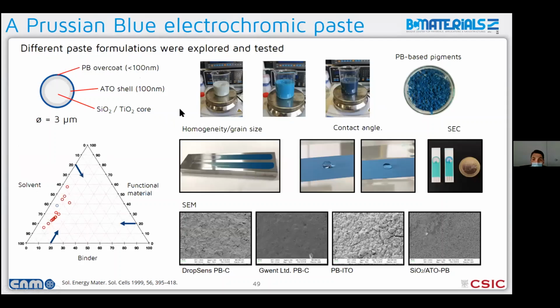So to formulate the Prussian blue paste, we know that when you screen print, you have layers, or coatings, that are definitely more than 5 microns thick, usually closer to around 10 microns. So that's a lot. So you need to make sure that the coating is going to be slightly conducting at least. So we looked in the literature, and we found material that is basically silicon dioxide beads covered in a thin antimony tin oxide shell. These are conducting, and then what we did was to grow the Prussian blue on top. So this is how the particles look at the beginning. They are gray, and then as you start growing the Prussian blue on top, you end up with a really deep blue pigment that you can then dry and turn into a paste.